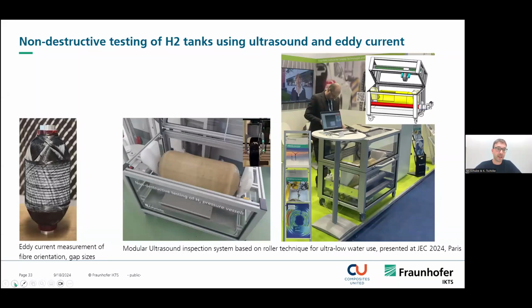On the left side, you've already seen these results using the eddy current measurement systems, but you can also use ultrasound to inspect these pressure vessels made of carbon fiber, maybe also made of glass fiber. And you can combine both methods, the eddy current and the ultrasound, into one inspection system. This inspection system is based on a roller technique. That means the ultrasonic probe is in this roll and can inspect the pressure vessels. This inspection system was already shown at the beginning of this year in Paris at the JEC.